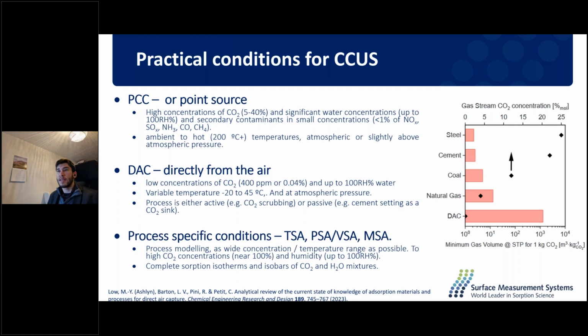But also, besides these particular process parameters, there are many more process-specific conditions that are encountered during a process. The way that these processes are being run in practice is either temperature swing, pressure swing, vacuum or moisture swing adsorption. This is how to desorb the captured CO2 from the material and regenerate it for a new cycle. And in here, there are many conditions which can be encountered. So high temperatures, low pressures, high humidities, extremely high CO2 concentrations if it's desorbed, for example, 100%. So the interest here is to know as much about the system with a complete isotherm, complete isobars of CO2.